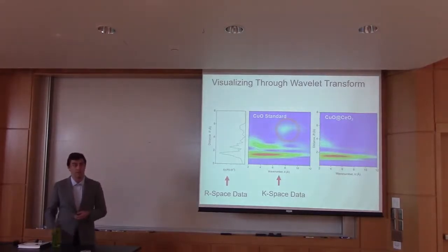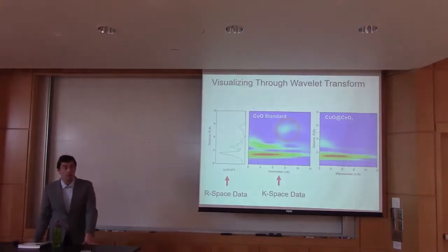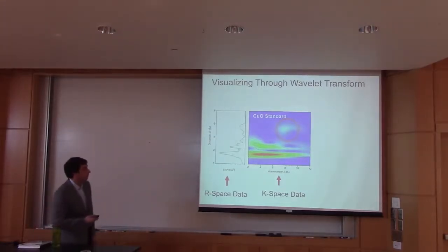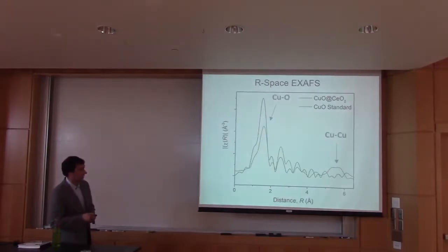You wouldn't see it scatter off the ceria either? It might be, it could be happening here, which are multi-scattering peaks, and very hard to index without modeling first, and this is preliminary data, so that hadn't been done.